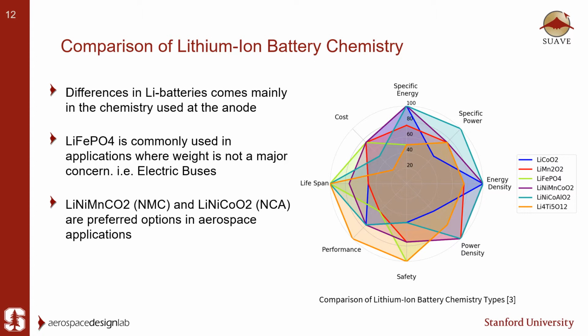With high scores in safety, performance, and cycling, we see from the spider chart that lithium iron phosphate is the best chemistry of choice for large electric applications where weight is not a significant factor. However, in applications where weight is very sensitive, such as in aerospace applications, battery chemistry such as lithium nickel cobalt aluminum oxide, which is NCA, or lithium nickel manganese cobalt oxide, NMC, are preferred. In this presentation, I will dive particularly into these two chemistries with particular emphasis on the NMC chemistry.